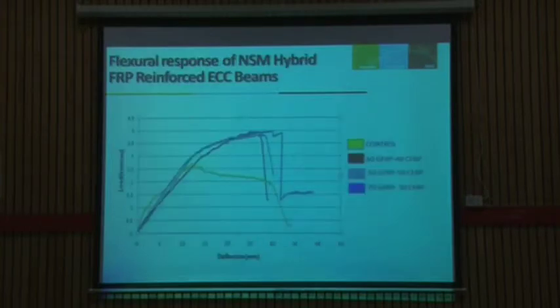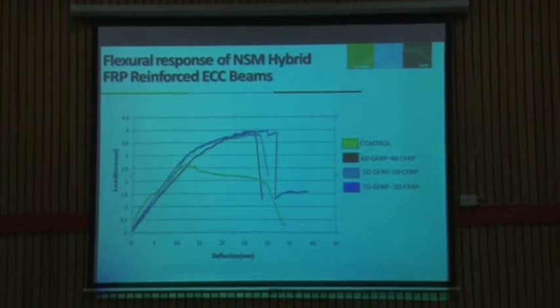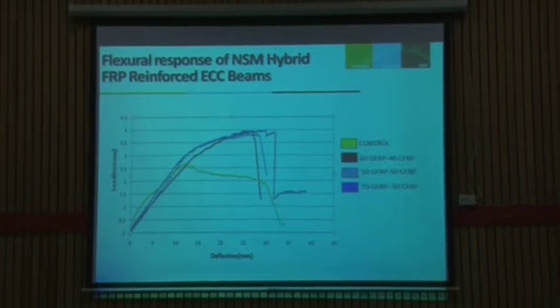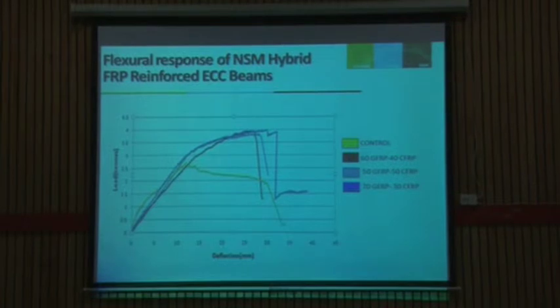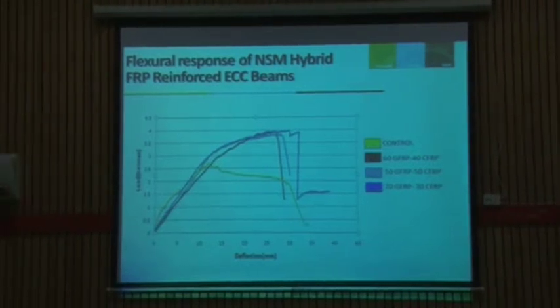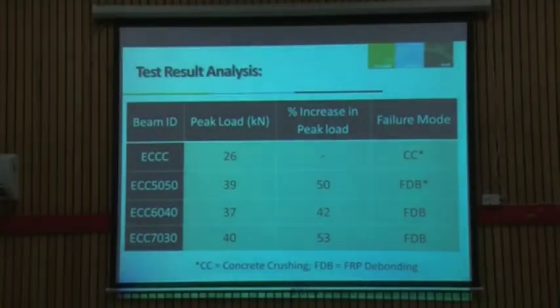Here we are comparing the response of all the control beams, and you see that there is significant improvement in strength with just 2 bars of 8 and 10 mm diameters tested, in 70 and 30% combinations. Although this strength has been observed with the debonding mode of FRP failure, it means that the full strength of FRP rebars had not been utilized sufficiently. So this is the debonding failure.